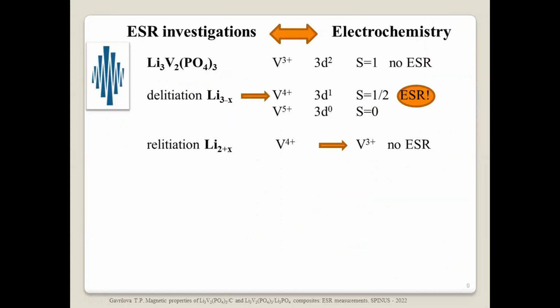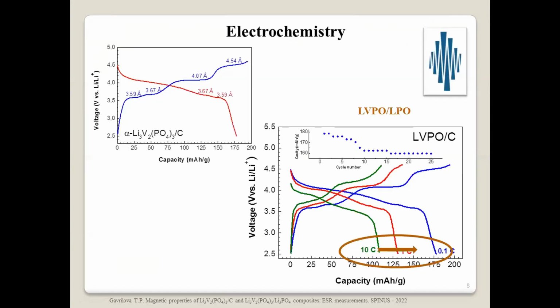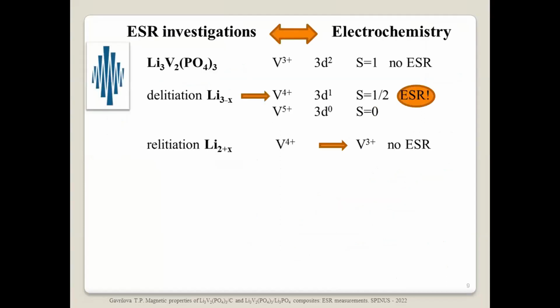Now, about ESR investigations. Let me return back. Here we can see the charge-discharge curve for the electrochemical cell. We suggest that during this process, lithium ions should be removed and then moved back into the structure of this lithium vanadium phosphate. But to prove this fact, we can use electron spin resonance measurements.